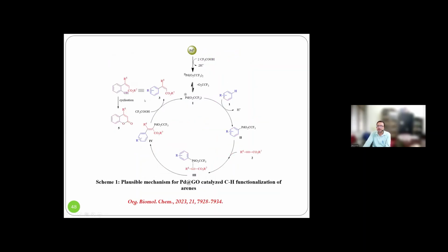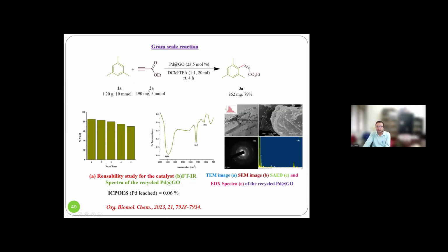This is the mechanism. This is not a very hard mechanism. Just insertion takes place, then addition, and then reductive elimination gives the product. Everything we did, reusability, then leaching we did. Actually, the leaching test shows how much catalyst leached out during the reaction. This is very important because in drug development, metal contamination of the product is one of the disadvantages we can say. So if the catalyst leaches low, then that catalyst is good actually. And then we identify the morphology of the reused catalyst by various techniques.